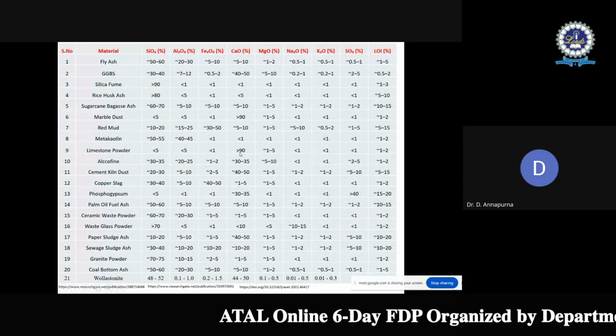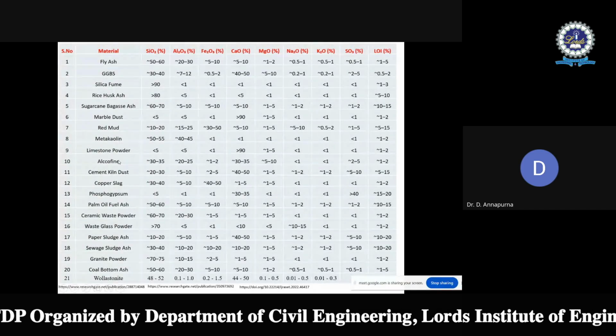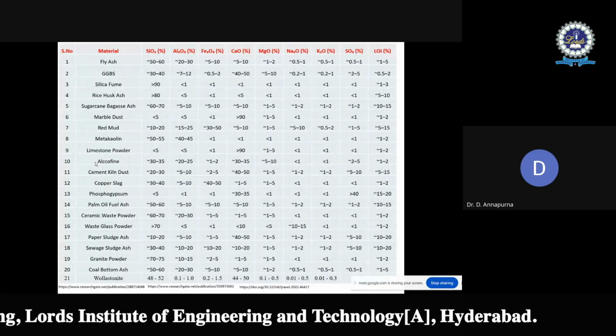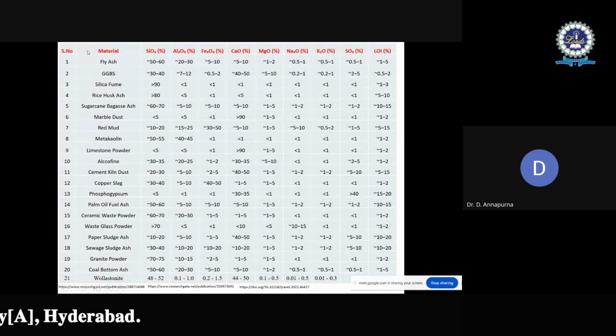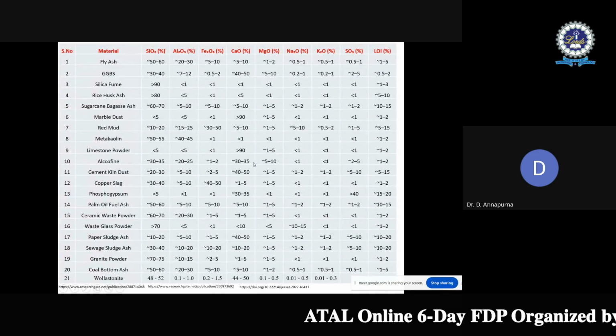Then limestone powder is also rich in calcium oxide. It also can be used as an admixture in the geopolymer concrete. Then Alccofine is nothing but a fine powdered or modified version of GGBS. Very, very finely ground GGBS is Alccofine. Similar to GGBS, Alccofine is rich in calcium, silica and alumina.